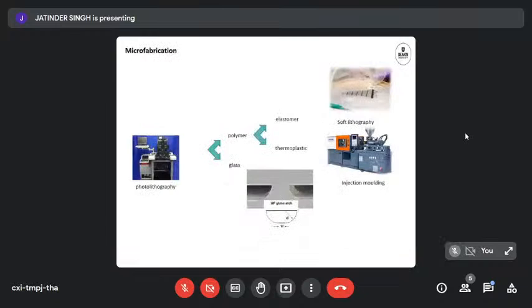Where we had traditional photolithography as the basis of all our microfabrication, where we then could do direct microfabrication by using photolithography to create an etching mask, to then do wet etching with hydrofluoric acid in glass and get these nice round undercut structures. The other option was to do polymer processing, still using photolithography to create a template, which then could be used to cast an elastomer, as done in soft lithography for replicating PDMS devices, or for thermoplastics, where we can use thermoplastic machining methods, injection molding or hot embossing, depending on the throughput that you want.